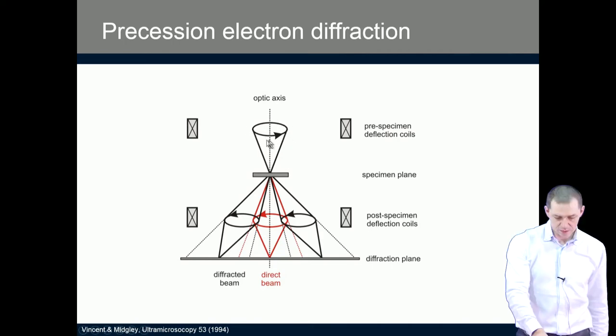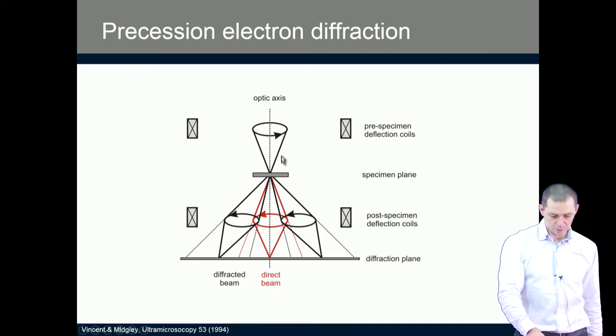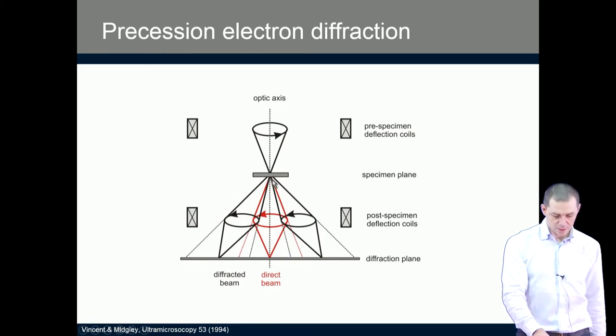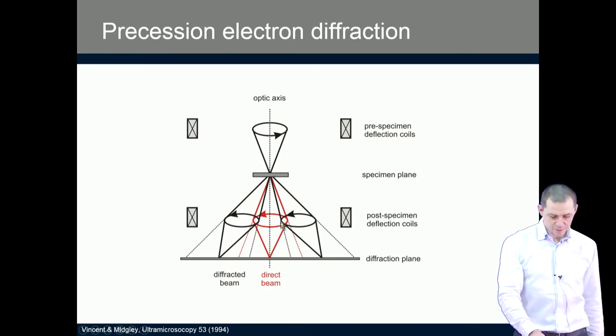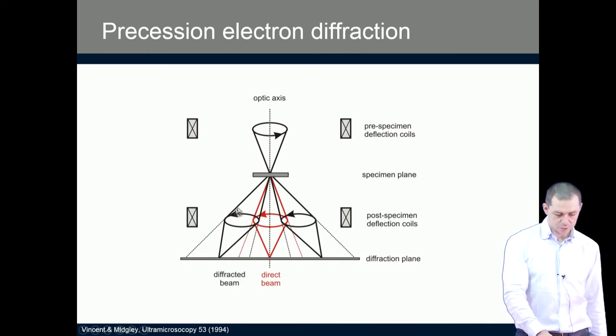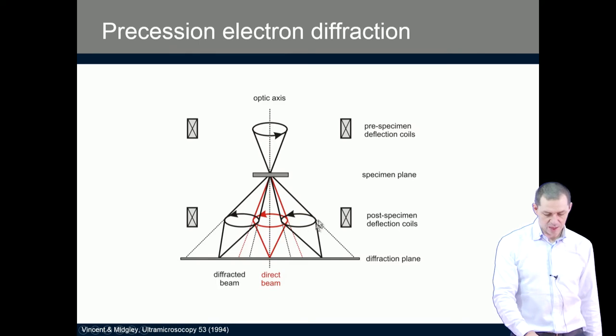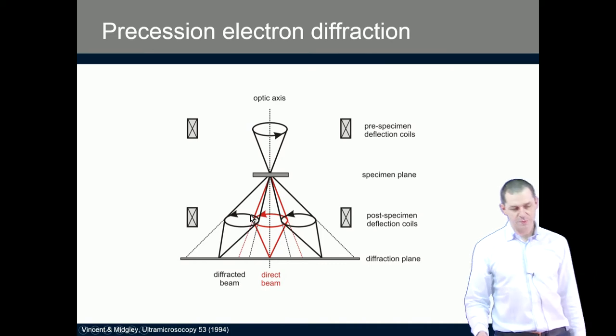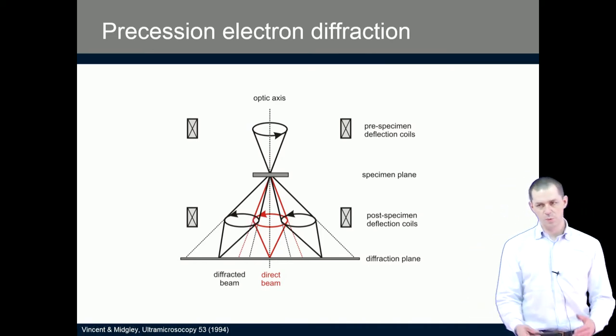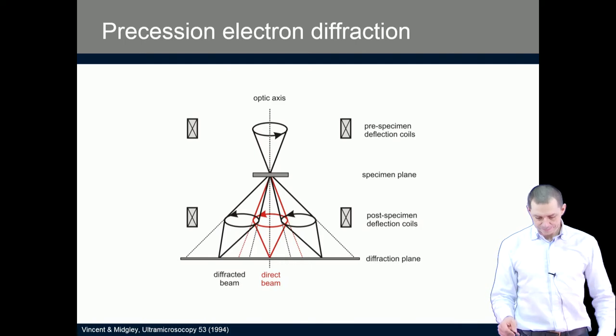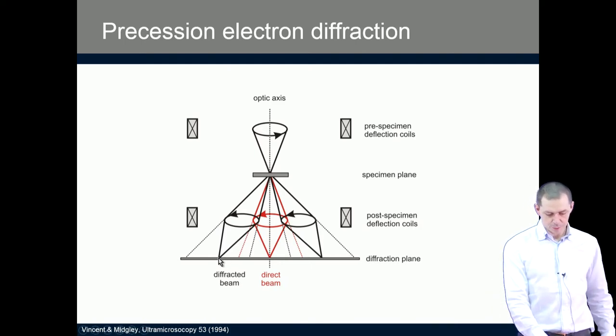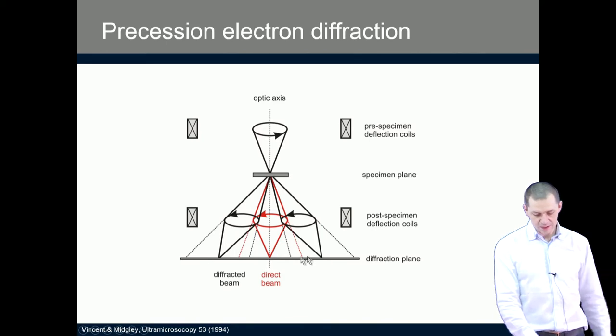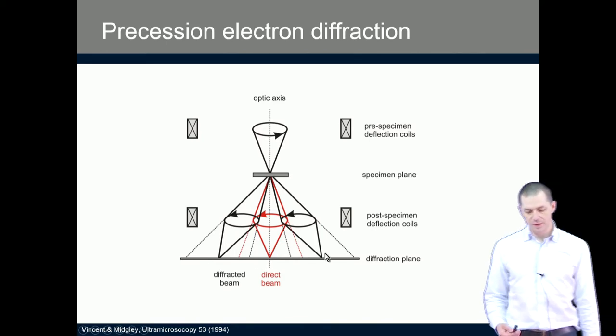The beam is moving along the surface of the cone, falling on the sample, or entering the sample, in the same position, and then the central or direct beam is also moving on the cone when it's leaving the sample, as are all the diffracted beams. But then we have another set of post-specimen deflection coils in the microscope, which can be used to focus the beams back to spots. So in the end, we get again a spot diffraction pattern in the diffraction plane.